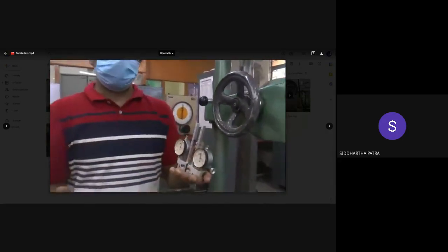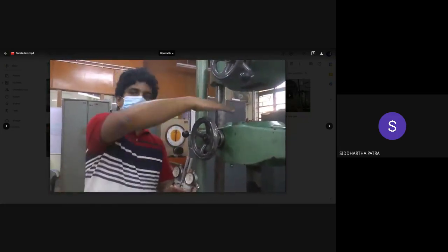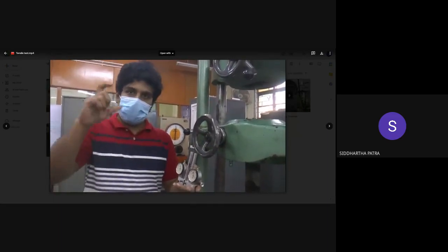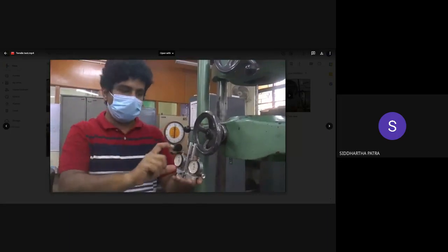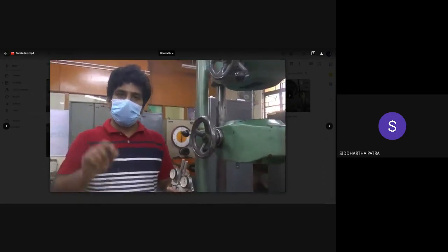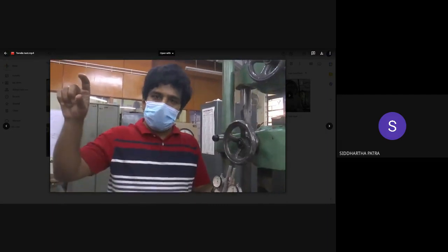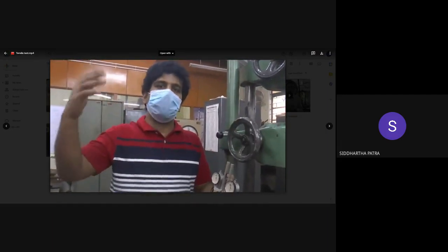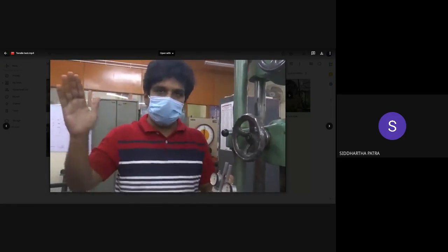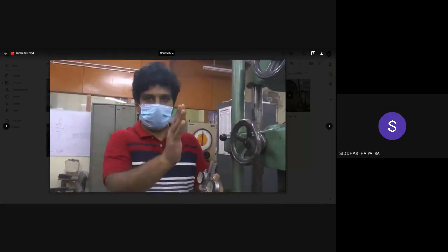Now I have mentioned three lengths. One is the total length of the specimen, about 350 millimeters. Then the effective length, which is the 10 millimeter diameter portion, and in that portion we are only taking a very small segment of 60 millimeters. The reason for doing that is that from the 12 millimeter diameter portion to the 10 millimeter diameter portion, there is a taper region, and in that the stress state becomes three-dimensional. It needs a smooth transition from three-dimensional to one-dimensional stress state.